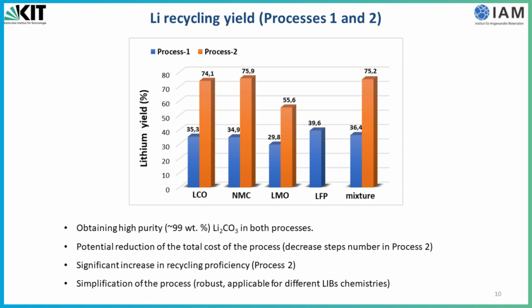What's exciting and important is that these processes are effective for all currently used cathode chemistries such as LCO, NMC, LMO, LFP, and, what is interesting, even their mixture. As a result, we can obtain high purity lithium salt, lithium carbonate. When we take a look at the processes, we can see that when we switch from process one to process two, we see potential reduction in the total cost of the process due to the decrease in the number of steps and significant increase in recycling efficiency. We can see that in the simpler process, we obtain lithium with up to 70% yield.